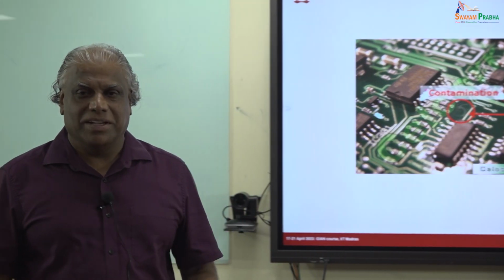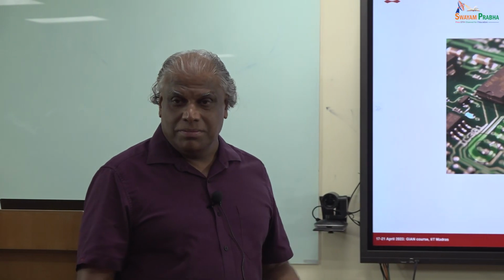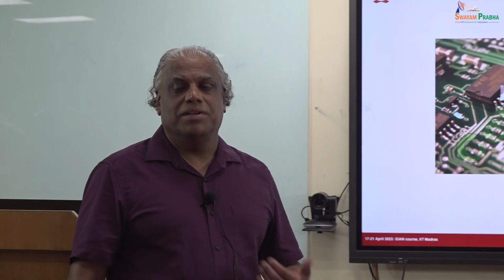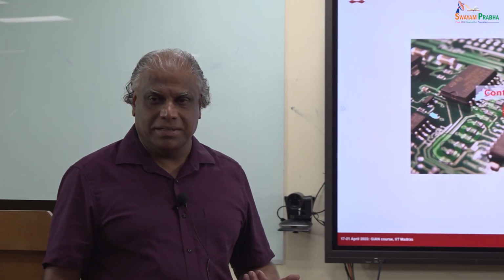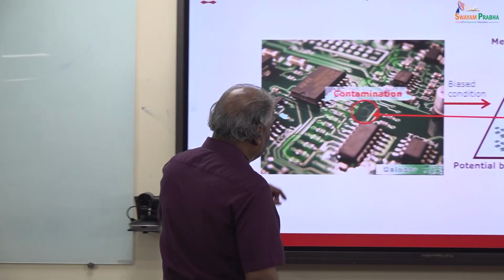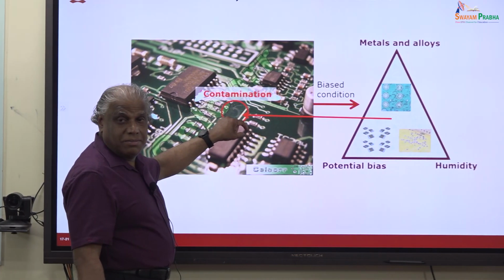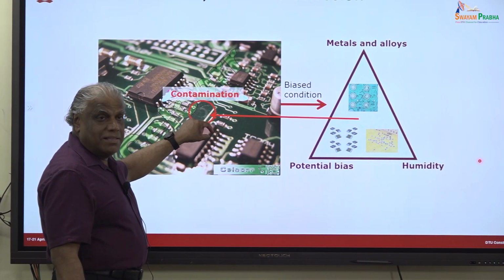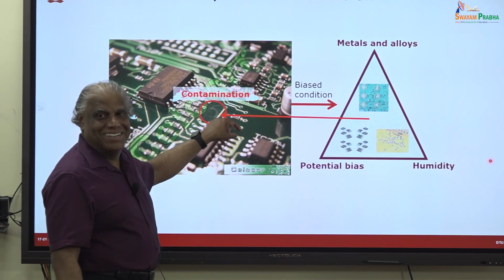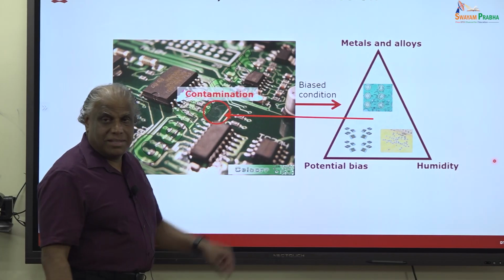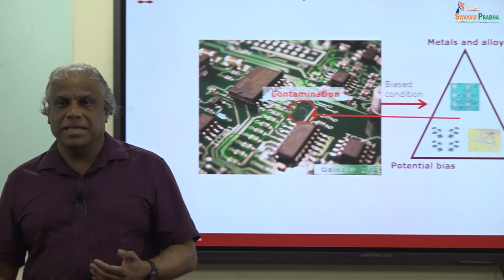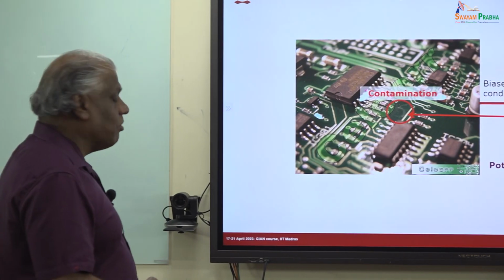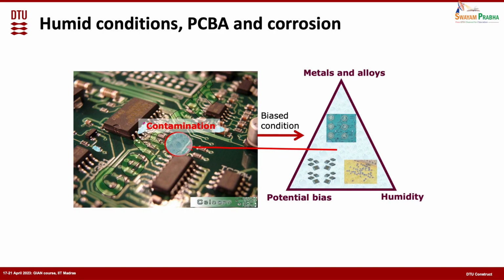You can see that when they manufacture ICs, it runs in a clean room. The reason is that when you take an integrated circuit, this contamination is much more important. Here we are talking about at least a few hundred micrometers of distance, and in the case of ICs, some distances are a fraction of a micrometer, nanometer-scale differences. So there this contamination becomes much more important. That's the reason they make it in a clean room. Also, of course, they want to avoid contamination in the semiconductor as well. So that explains how the combination of factors which is important for corrosion is coexisting on the PCB surface.